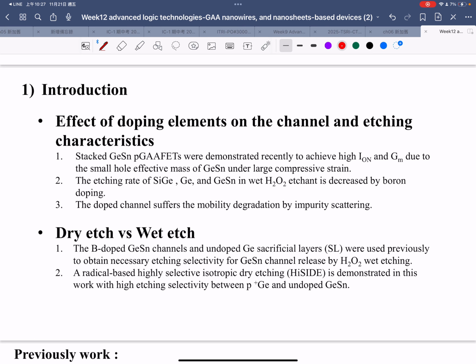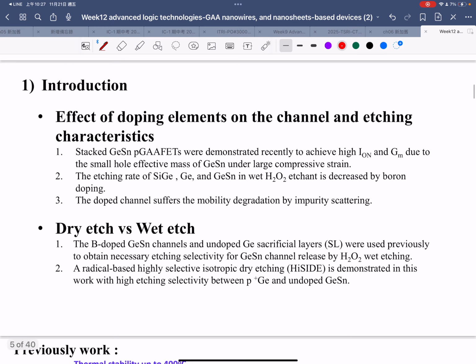The effect of doping on the channel and the etching characteristic of stacked GeSn pGAAFET are demonstrated recently to achieve high on-current and GM, but with high on-current, the off-current is also high, because their high on-current is due to the small hole effective mass under large compressive strain, and also the band gap becomes smaller, so the off-current increased a lot.